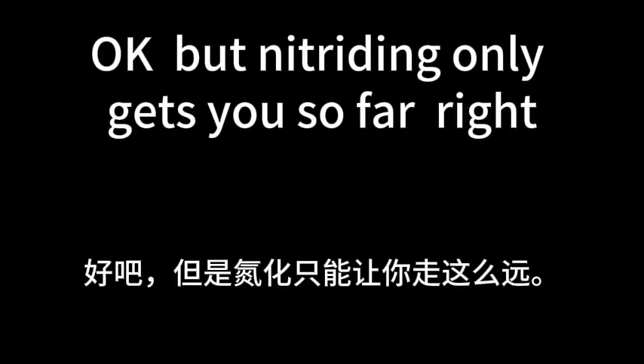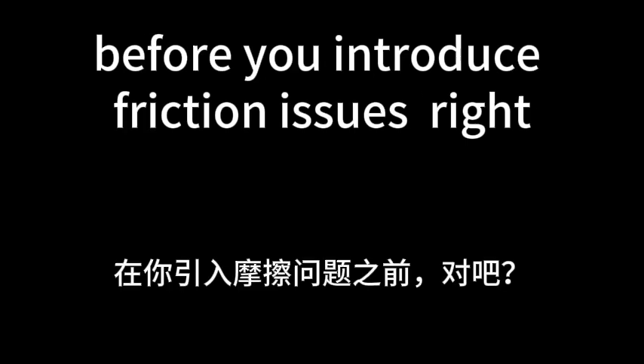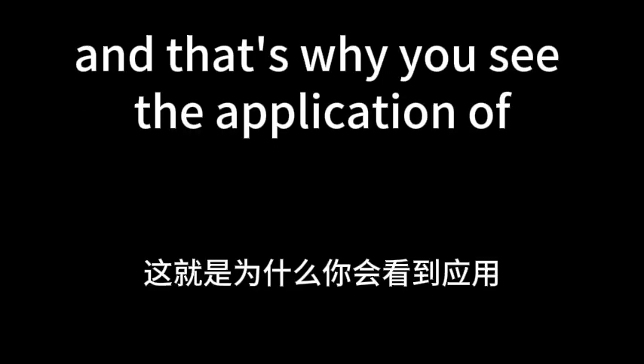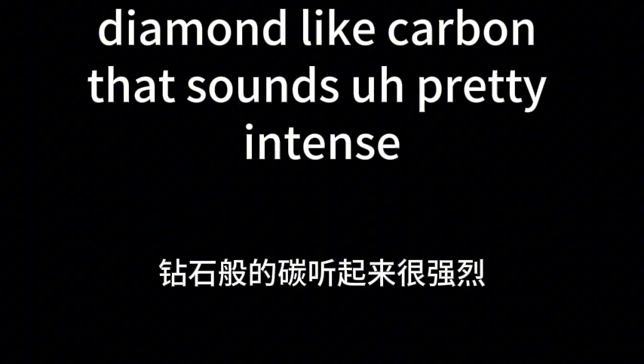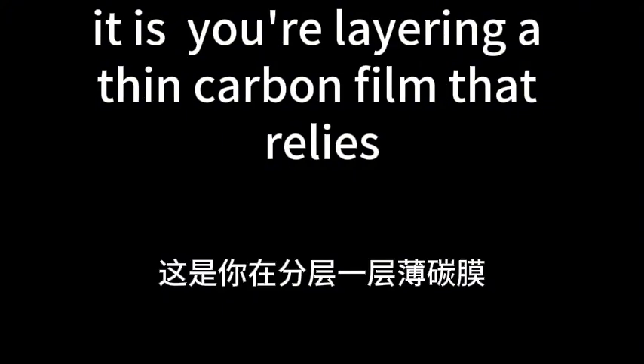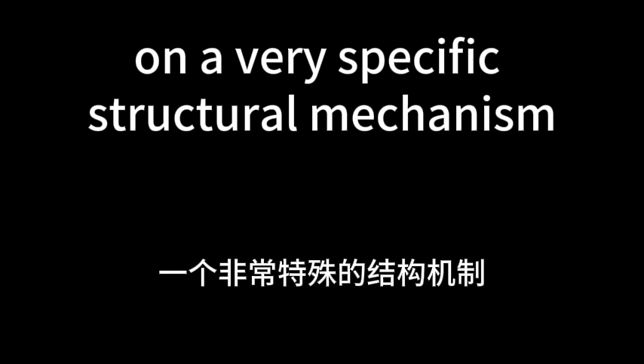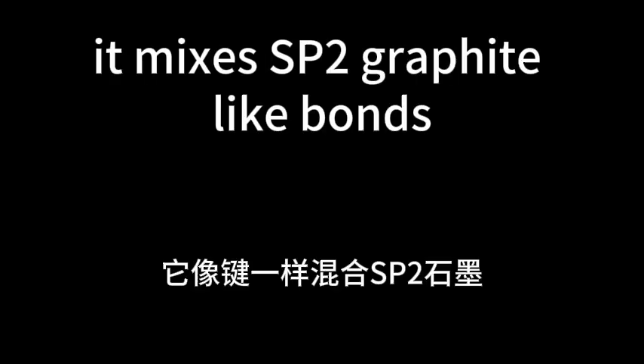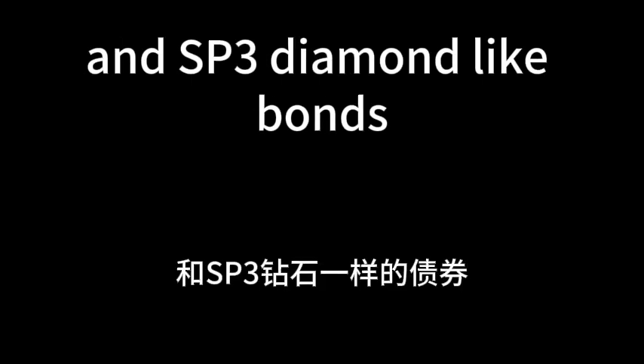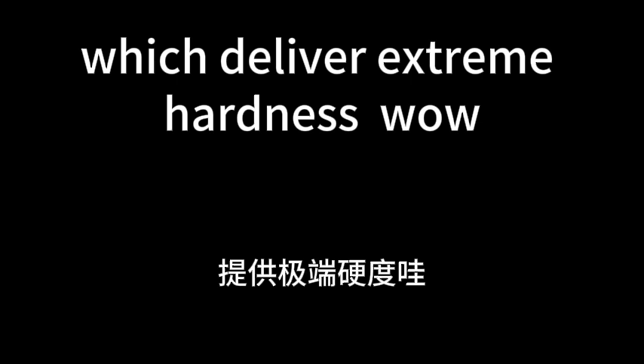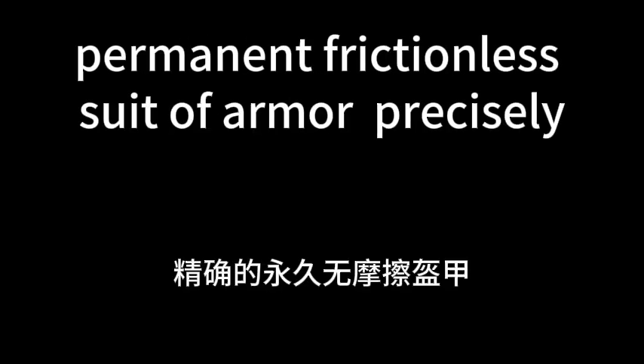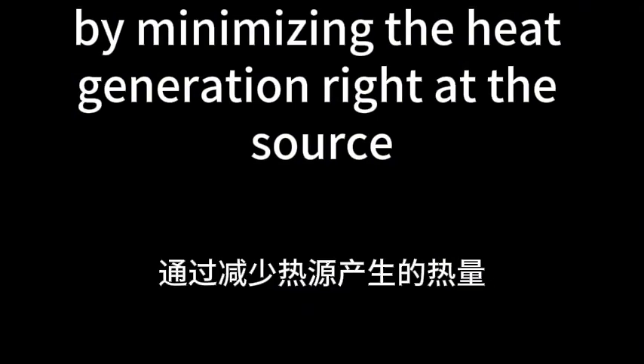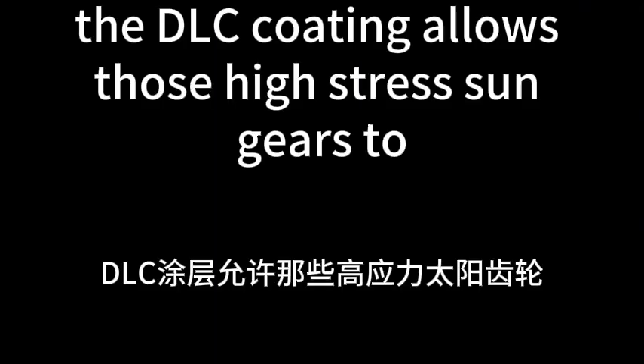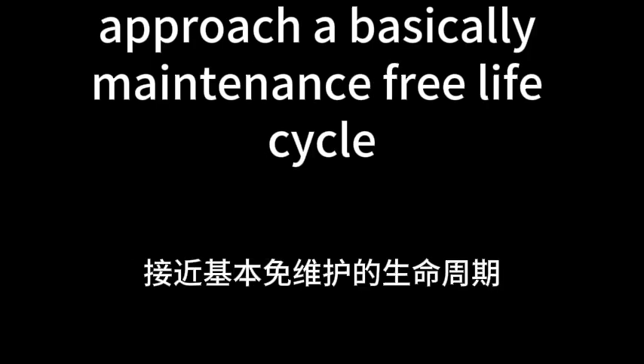Okay, but nitriding only gets you so far, right? Before you introduce friction issues. Right. For components rotating at extreme speeds, like sun gears, you hit a thermal wall. And that's why you see the application of DLC, or diamond-like carbon coatings. Diamond-like carbon, that sounds pretty intense. It is. You're layering a thin carbon film that relies on a very specific structural mechanism. It mixes sp2 graphite-like bonds, which provide ultra-low friction, and sp3 diamond-like bonds, which deliver extreme hardness. Wow, so it is essentially giving the gear a permanent, frictionless suit of armor? Precisely. By minimizing the heat generation right at the source, the DLC coating allows those high-stress sun gears to approach a basically maintenance-free life cycle.